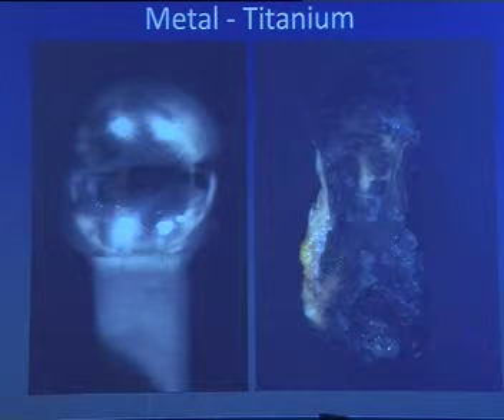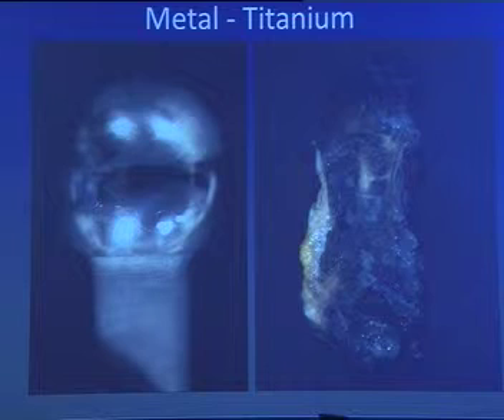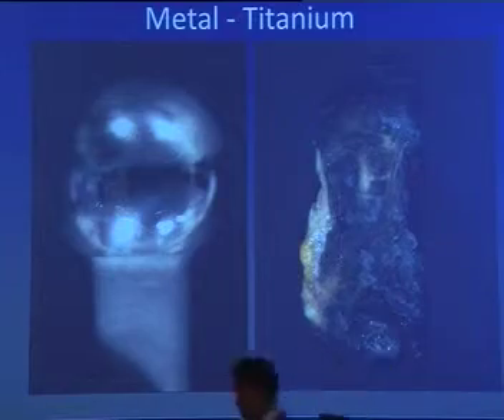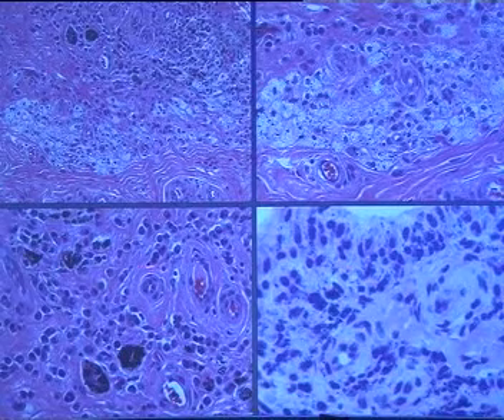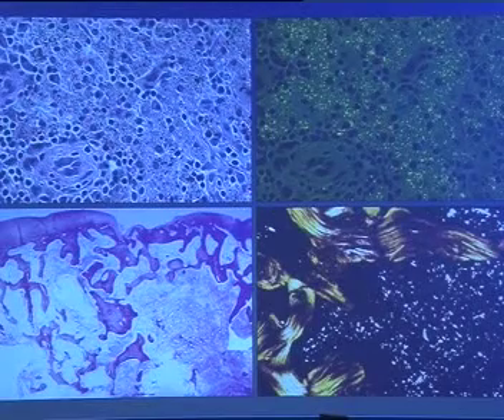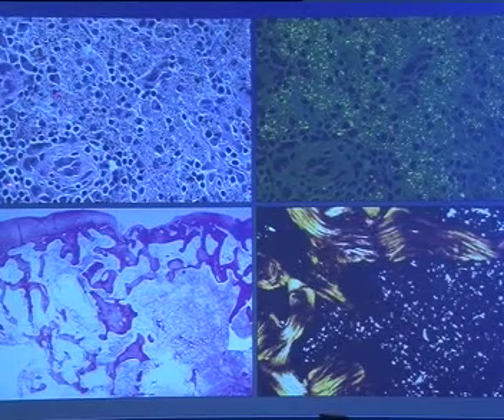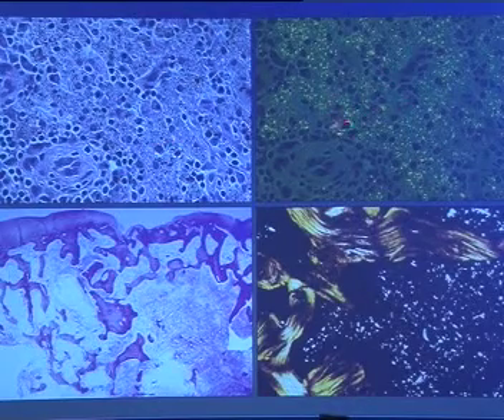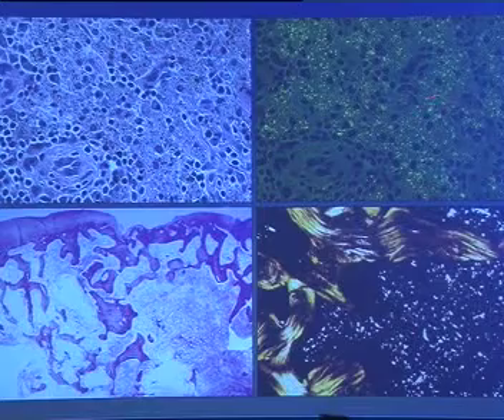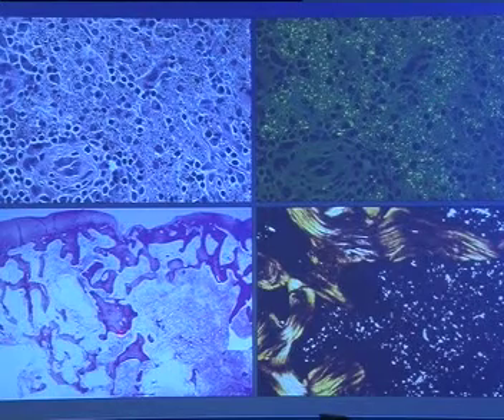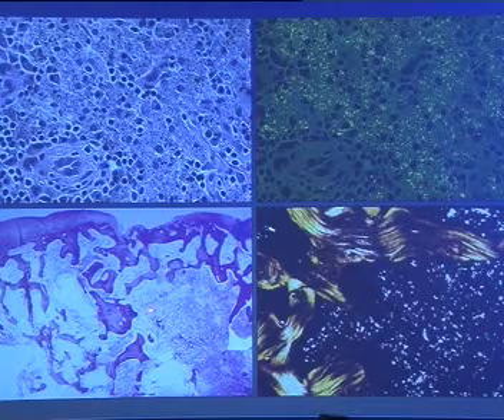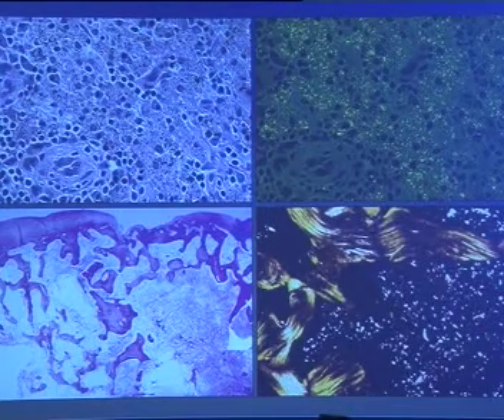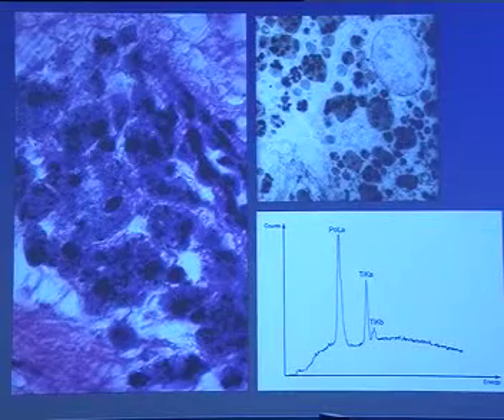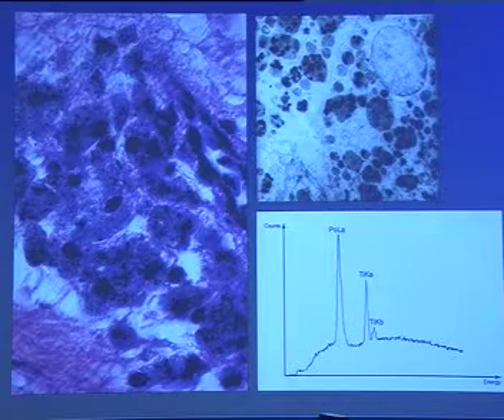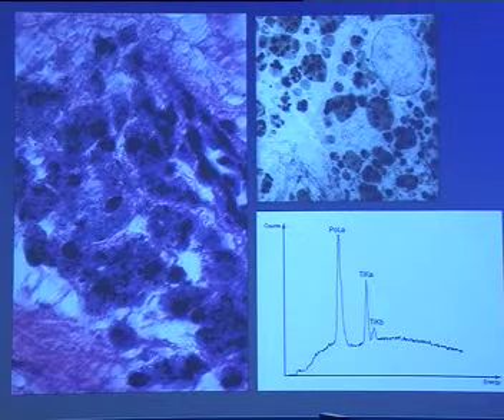And my colleagues and I were the first to report this titanium shedding in 1987, Agins et al., at Hospital for Special Surgery, because till then it was considered artifact in the lab, but in fact this is what metal looks like on microscopy. And furthermore, you see that it involves not only the soft tissues, you polarize it, it's dot-like as opposed to those linear shards, fibers of polyethylene. And in fact, this is a section of bone, cartilage, and trabeculae. And you see that it also has a propensity to infiltrate because it's an inflammatory response to this foreign material. And higher magnification to demonstrate clearly that these macrophages have engulfed these particles of metal.